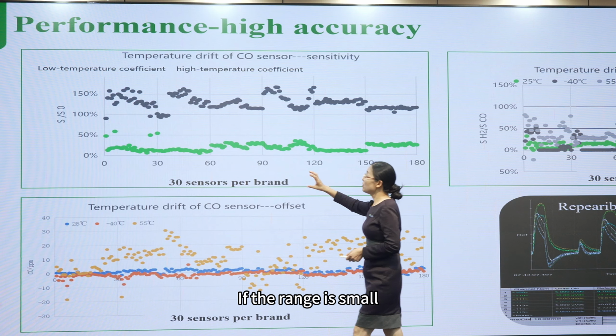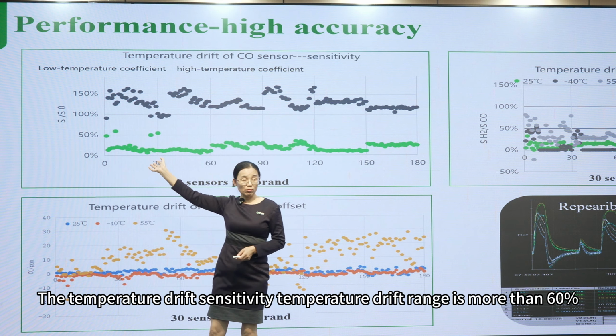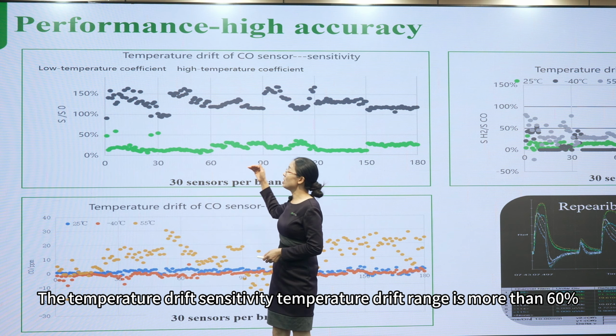If the range is small, you can do a better compensation. For the first manufacturer, the sensitivity temperature drift range is more than 60%. That means even if we use the middle part, the sensor has a minus and plus 30% error, just arising from the temperature compensation. Together with the error of the sensor itself, it cannot give us an accurate result. But for these last two, the range is very small, so the compensation will work very well.